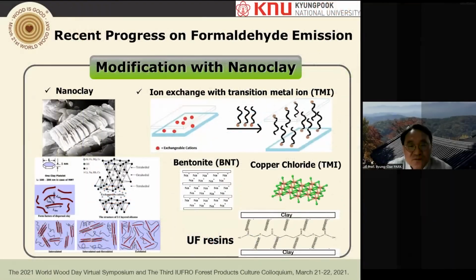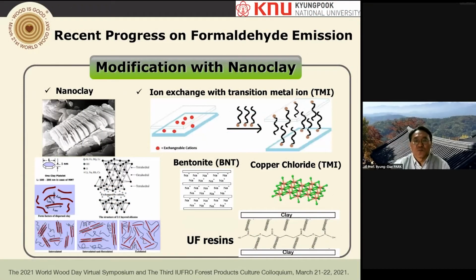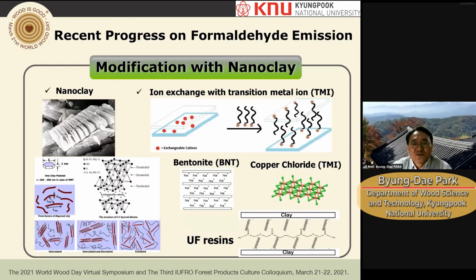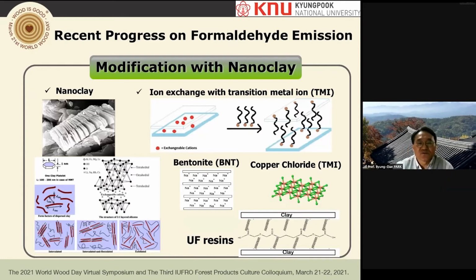So the idea is very simple: we try to modify the low molar ratio resin with nanoclay. As you know, nanoclays are layered structures like this, about 1 nanometer thick, and they also have exchangeable ions, which are sodium cations between layers. Once you mix the nanoclays with the polymers, some of the polymers sit between the nanoclay layers, or some of the nanoclay layers are exfoliated.